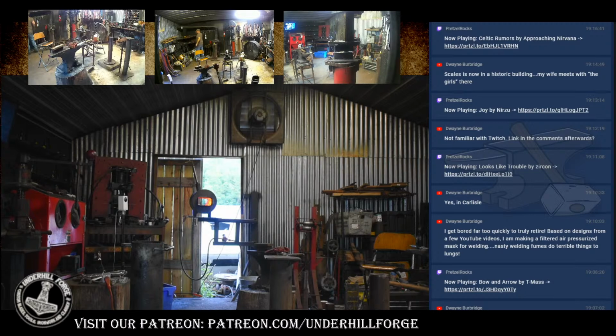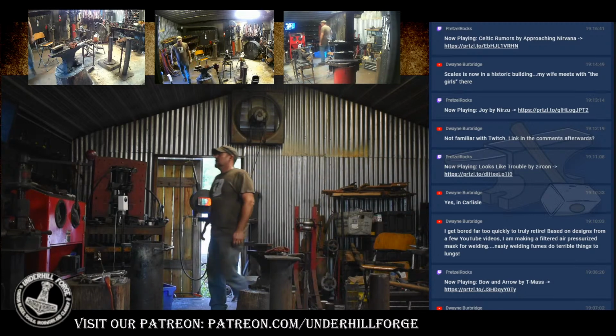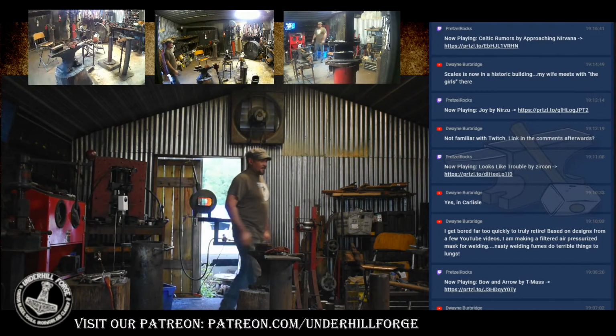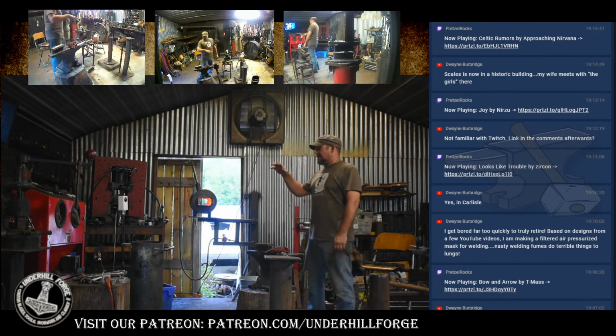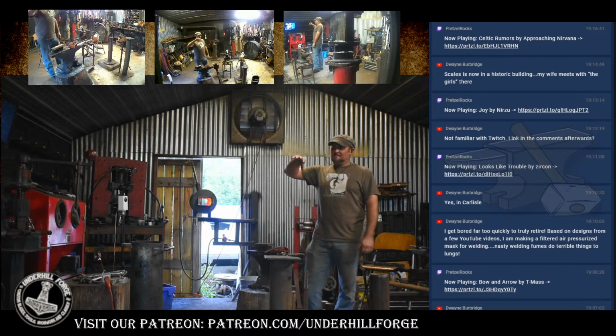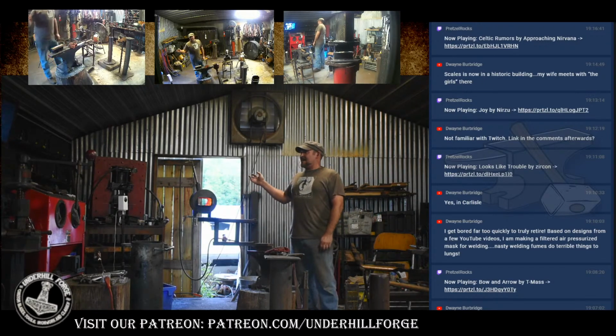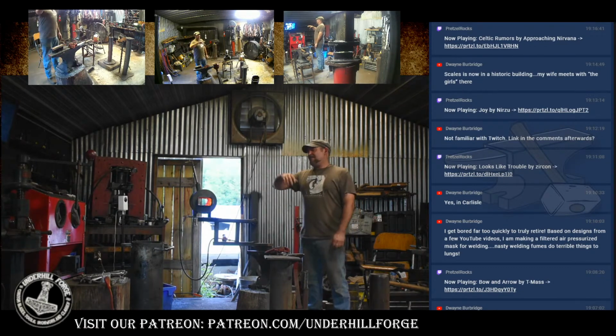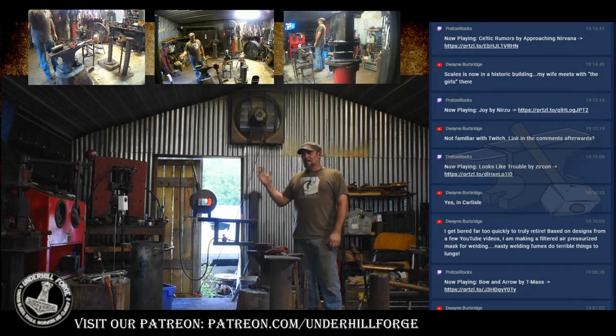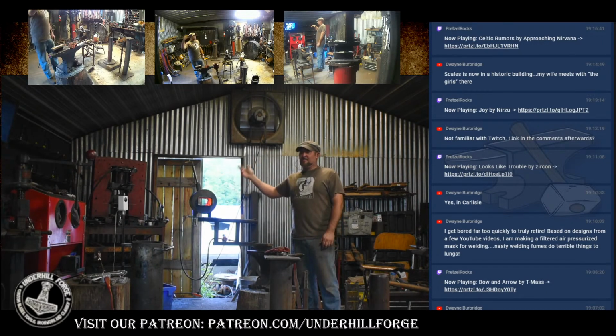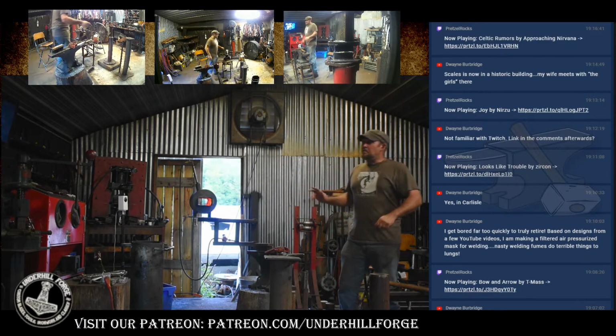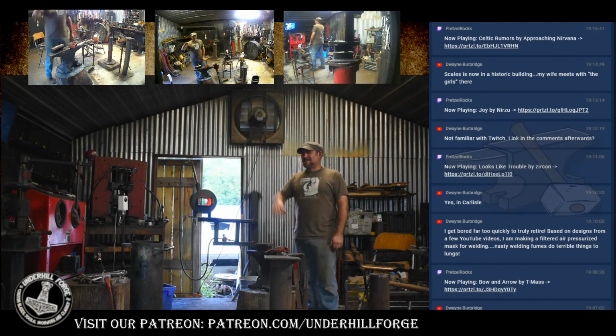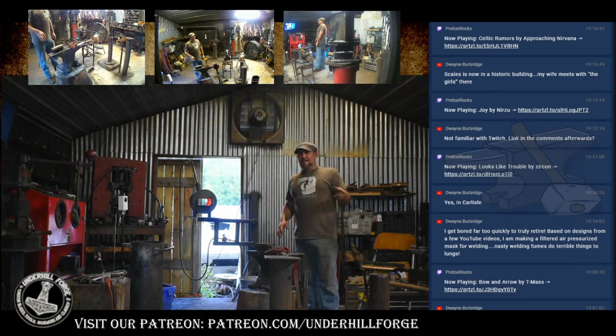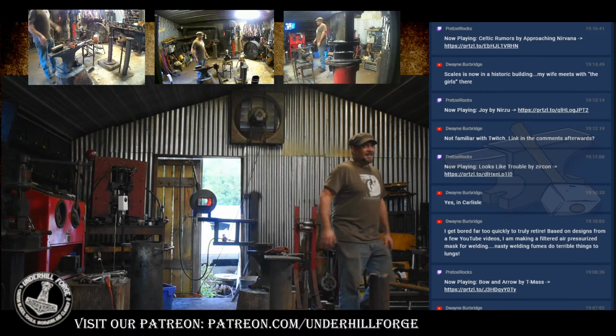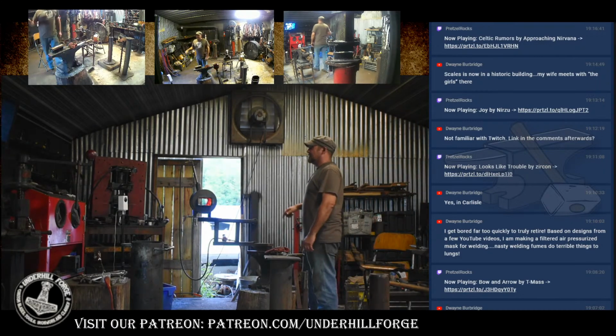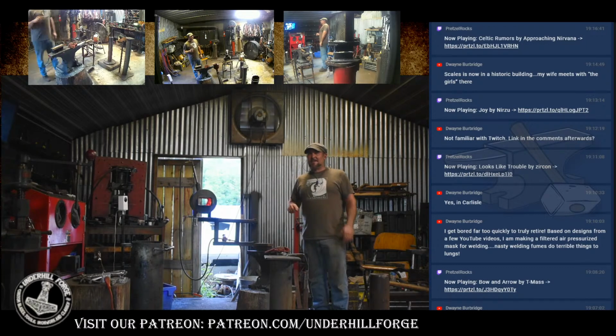But during my cycle, I set it up during the winter when it's nice and cold here in the shop. So in between the temperatures I have it going for, I'm holding it, say, 385 degrees, and after it holds that for an hour and a half, I have it go to 80 degrees, hold that for a few minutes, and then it goes up to 405 degrees, or, you know, I'm just throwing those numbers out there. But the 80 degrees is the issue. I realized something that was being tempered in there last night never hit the second cycle, because the oven itself never cooled down to 80 degrees on the inside.